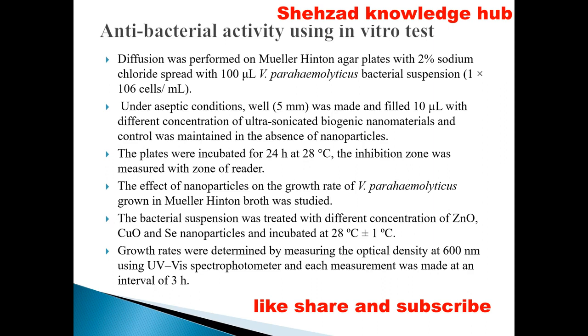Antibacterial activity using in vitro test. Diffusion was performed on Mueller-Hinton agar plates with 2% sodium chloride, spread with 100 microliters of Vibrio parahaemolyticus bacterial suspension. Under aseptic conditions, a 5 mm well was made and filled with 10 microliters of different concentrations of ultrasonicated biogenic nanomaterials, and a control was maintained in the absence of nanoparticles. The plates were incubated for 24 hours at 28 degrees centigrade. The inhibition zone was measured with a zone reader.